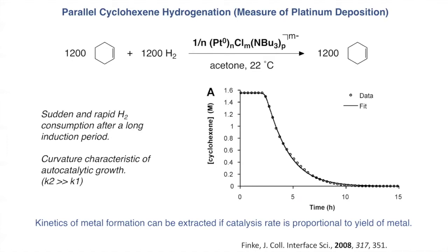And so, this pause, this delay or induction period for the first couple of hours, and this very rapid consumption process, this is a sign of autocatalysis. Something gets made in those first couple of hours, and as you make it, the reaction system sort of turns on.